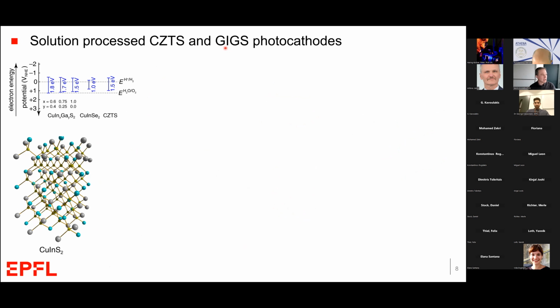photocatalytic water splitting reaction, also because the band gap of the semiconductor can be tuned by changing the composition of the materials. Specifically for hydrogen evolution, having a good driving force, having the conduction band above the zero versus the reversible hydrogen potential is quite advantageous. So converting the selenide to a sulfide raises this band gap and allows us to get a little bit better performance for the hydrogen evolution reaction.